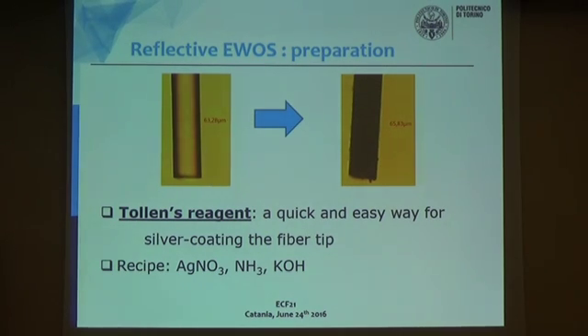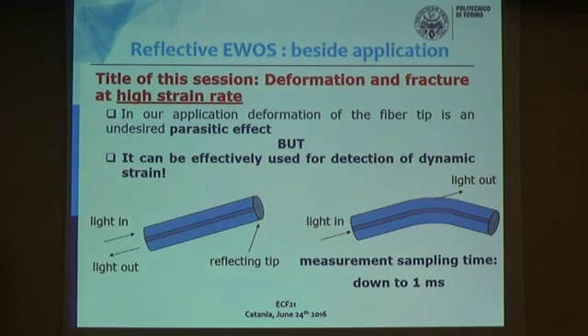We are making measurements, but the first results demonstrate that this kind of sensor works as well as the one I showed you in transmission. So it's a promising way. Just to conclude and to be closer to this session, on deformation and fracture at high strain rate, we can use those sensors for strain as well, because if you take the fiber tip and you bend it, it is very sensitive to strain. Of course, in our application, we embed the fiber, and we don't want the strain to corrupt the measurement of diffusion of water. But in some cases, it's possible to measure strain easily with this system.